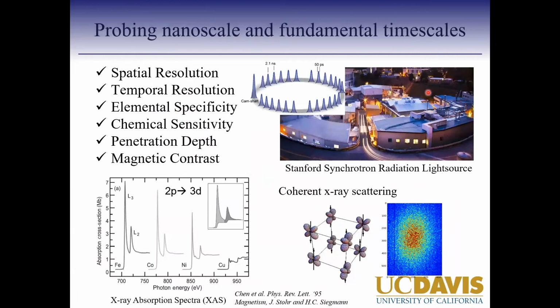And the way we study that is utilizing synchrotron light sources. So this is an image of the Stanford Synchrotron Radiation Light Source, where we have done some of our X-ray imaging work. And the advantage of going to these sources is, one, you get billion times higher X-ray intensity than you can get in an X-ray source in the lab. Because you're using X-rays, you get spatial resolution, so you can look at the atoms or any orbital charge ordering which you want to study. Because X-rays generated in these sources have a pulse width of about 50 or so picoseconds, it also gives you temporal resolution to study these systems.